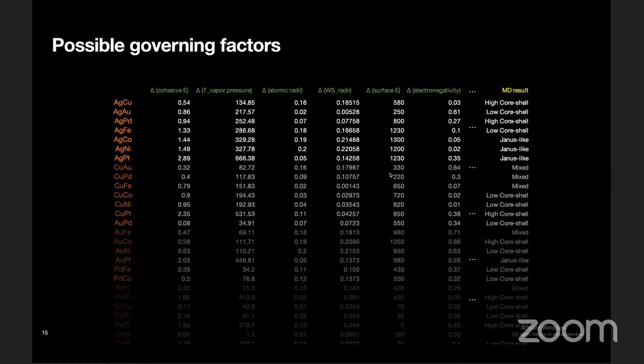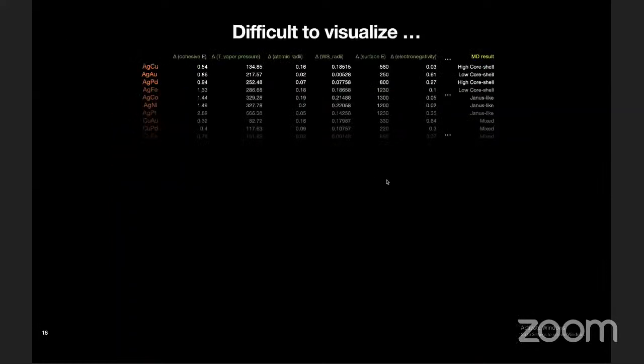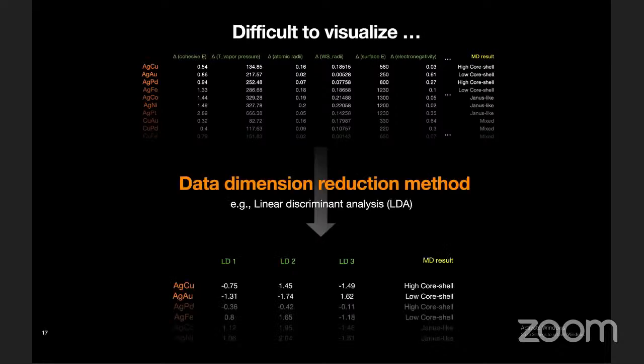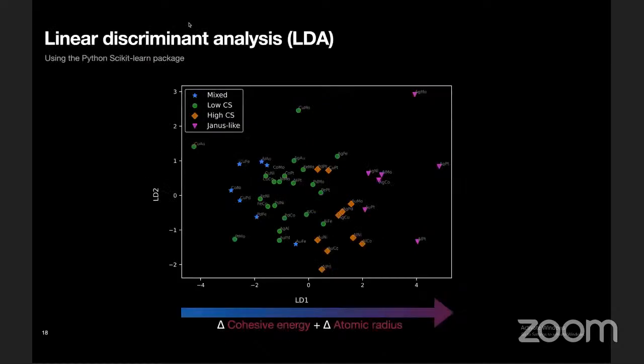And the easiest way would be to visualize the whole thing to see the relationship between the features and the MD results. But as we have many features, it was hard to visualize it. So what we did was that we used a data dimension reduction method, such as linear discriminant analysis, LDA. Using LDA, we could reduce the 8-feature dimension into 3 dimensions, but with minimal loss of original information. So here are the results of such analysis. It can be done quite easily using a Python package, by the way.